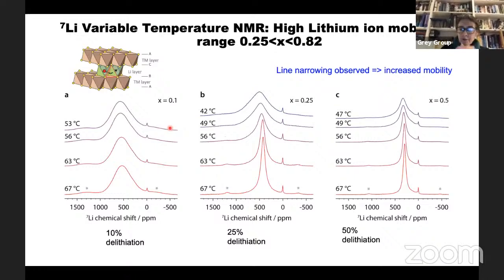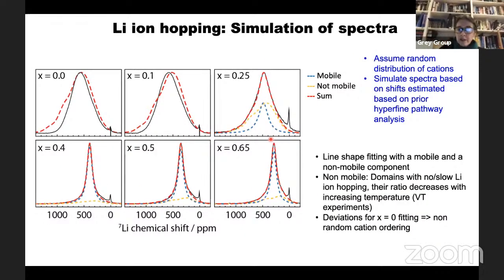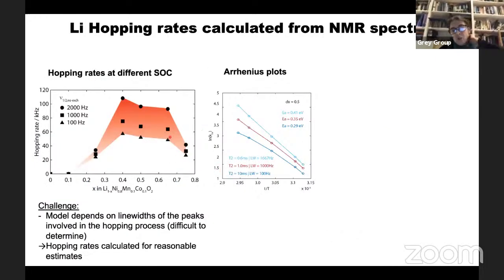Now, again, for those of you who've started to do a little bit of NMR spectroscopy and maybe even doing part 3s, will come across the idea of motional narrowing. And so if you have ions hopping from site to site and they hop fast enough, you don't see the individual environments, you just get an average. And so what we're watching here is when you go from even 40 degrees to almost 70 degrees, you get a narrowing of the signal as the lithium ions are hopping. And we can go through sort of analysis of this and simulate all the spectra as a function of state of charge. And we can extract, depending on the model, hop rates for the ions in the structure.